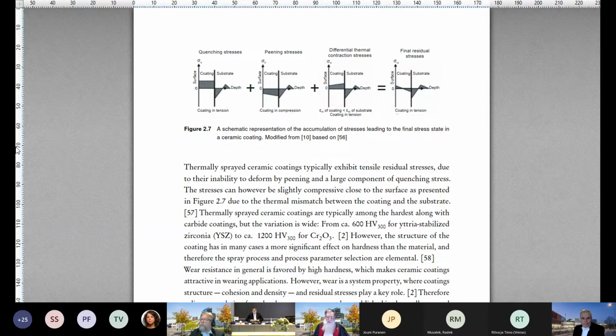If you wanted to get a near net shape and have the coating actually fall off, and people do that. So there are instances where crack propagation or relief of the coating from the job to get a near net shape, which is then post-processed, might be an attribute. But I think we'd all agree that sometimes we highly want compressive stresses.